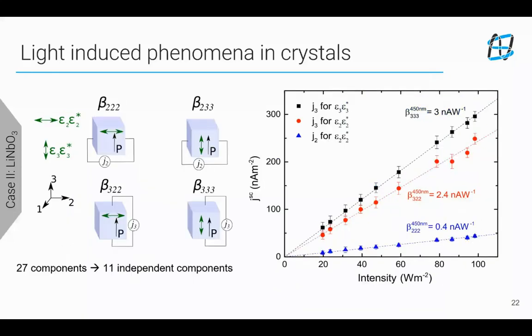Then we wanted to see whether it is only via the polar axis that we can see current. That is what most people think: that along the polar axis, when we measure the current, that is how we get most of the current. And orthogonal to it, traditionally, people have thought for several years that you wouldn't get current, because the atoms are arranged non-centrosymmetrically, and most of what you'd get is only via the polar axis. But that is not true. What we saw was, when we shone light orthogonal to the polar axis of the crystal and measured current orthogonal to the polar axis, even then we could actually see a bit of current coming out.